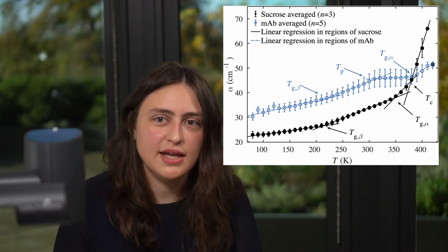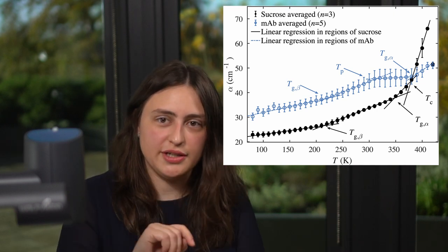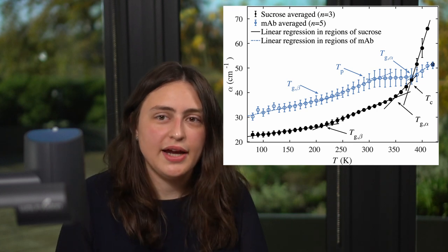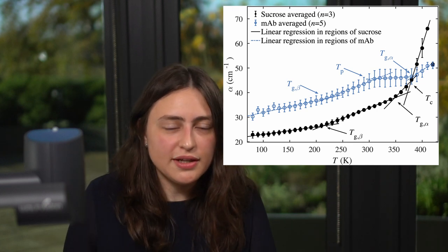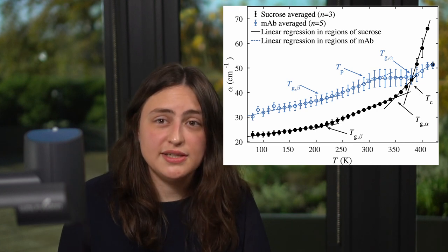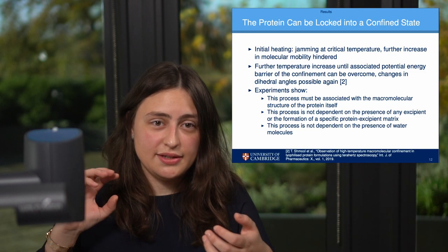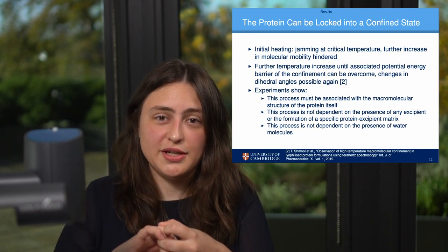At that plateau, what we think actually happens is that the protein is jammed. It is physically locked into a conformation and cannot get out of it unless we put in a lot of energy. While it is there, we don't have any new motions becoming available — we're trapped in that energy well.